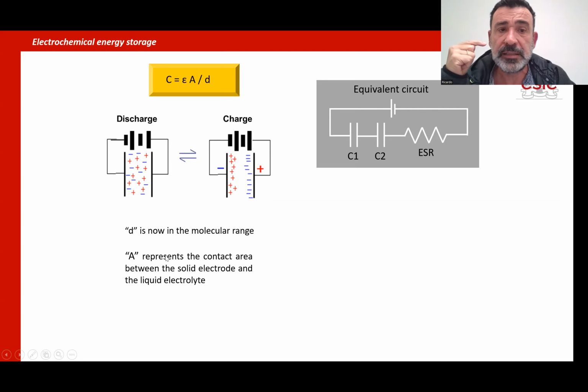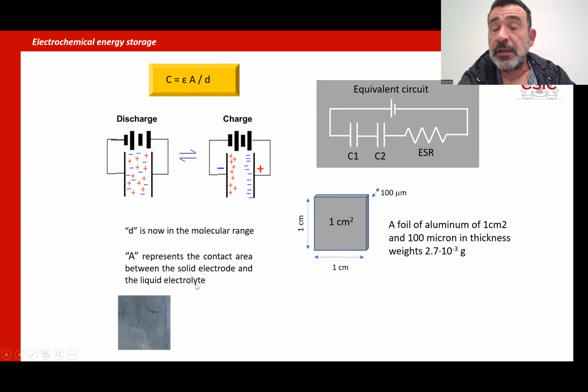Okay, and the second, a bit more complex, is A. A represents not anymore the surface of the aluminum plate, but the contact area between the solid electrode, the aluminum, and the liquid electrolyte. If you have, for example, 1 square centimeter of aluminum, the surface area in contact with the electrolyte is 1 square centimeter. Nothing special about it.